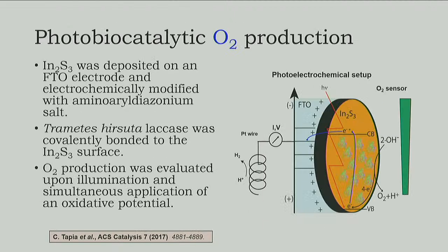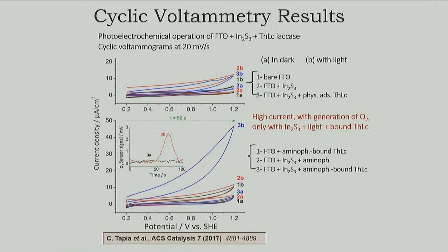So we immobilize this on the electrode that is expressed here. We put a layer of this material and later immobilize the enzyme on the surface. And now at this time we improve our system. No more enzymes for checking how much oxygen we're producing, but we got an external sensor that is going to tell us how much we are producing here. And also very important, how much can we decrease these 1.2 volts we have to apply for making the system work. So here we get some answers.